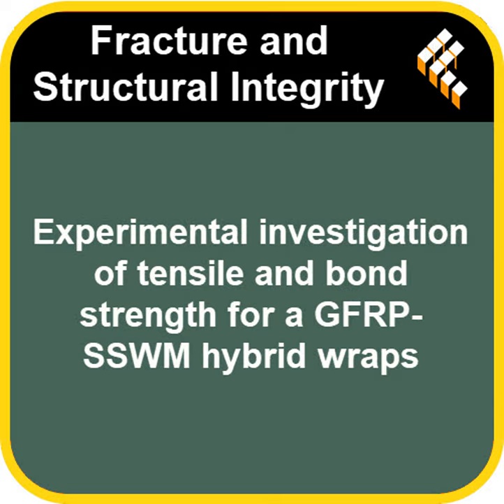Okay, makes sense. So how did they actually test this hybrid concept? What did the experiments look like? Well, the main goal was pretty clear. Investigate the mechanical behavior. How strong are GFRP, SSWM, and these hybrid wraps? And how well do they bond? Right. So they used coupon specimens for tensile tests, basically pulling them until they broke. 42 of those. Okay. And then 48 dumbbell-shaped specimens to test the bond strength with concrete.